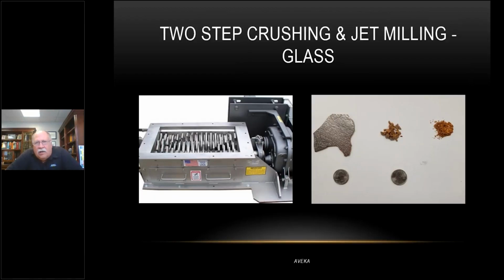Now, one of the real interesting things about all of this processing is that with grinding, many times you have to do this in multiple steps. This is an example here where we received sheets of glass, and these sheets are big, but they want it ground up to around 5 microns. If we put sheets of glass in a jet mill, nothing would happen. So what we did in this particular case is we did a two-step process, a two-step crushing and jet milling.